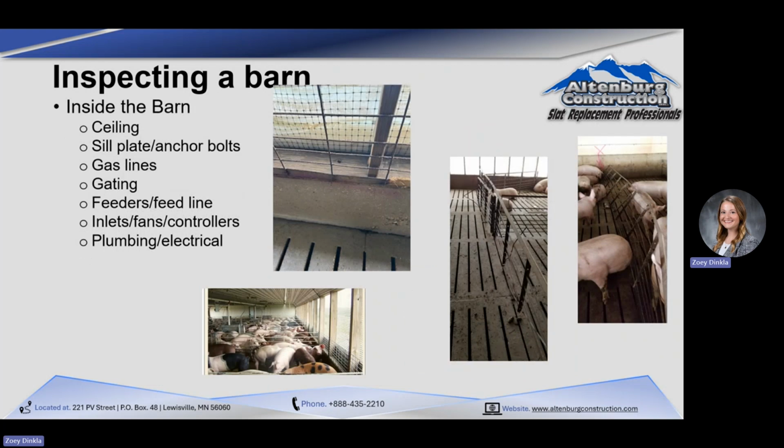As we move inside the barn, we spend a lot of time inspecting barns, and the number one item I see that really gets neglected is this sill plate. There should be an anchor point there every so many feet. In the earlier barns, this is a 2-foot stem wall. The pigs, when we designed these barns, were only 240 pounds, but today they're 320. So they're peeing and pooping in that sill plate. Those early anchors weren't necessarily galvanized or stainless steel, so they just rot off. I saw during a derecho several instances of straight line winds where it literally just shifts it right off that stem wall. It's really cheap and easy to repair. It doesn't take much, particularly when you have your hog paneling off, to re-anchor that down. It is a pretty critical component to keeping that barn attached when you have either straight line winds or tornado situations.